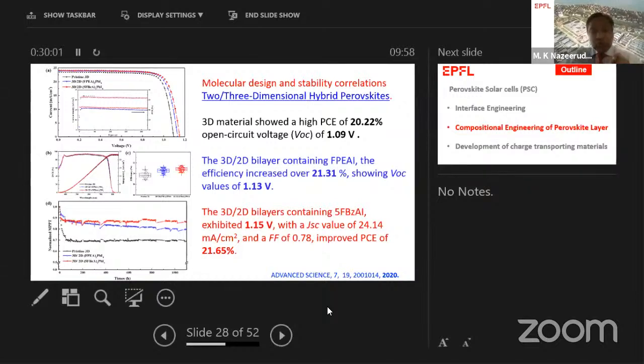When we deposited the two-dimensional perovskite involving fluorophenylethylamine, the power conversion efficiency increased from 20 to 21%, and the VOC went from 1.09 to 1.13. Changing the cation from fluorophenylethylamine to pentafluorobenzylamine, that's the red line, you can see the VOC further increased from 1.13 to 1.15. The power conversion efficiency increased further to 21.65. It's a small increase in the power conversion efficiency, but the stability is remarkably high compared to our reference sample.